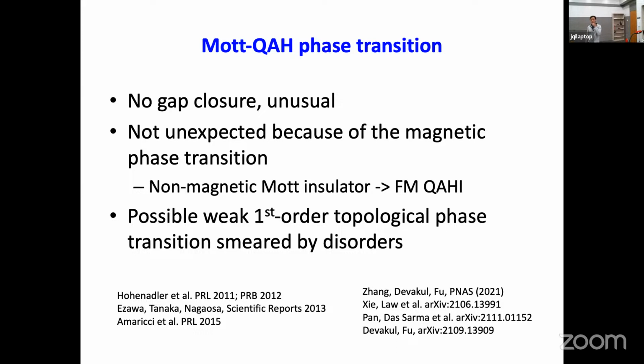It is also possible for homo bilayer, but I actually don't know what determines under what situation you will have a topological phase transition with gap closure, and sometimes you don't have a gap closure. The topological phase transition has not been seen there, right? I mean, in the homobilayer, we have seen actually from quantum spin Hall to an anti-ferromagnetic insulator, but not this type.